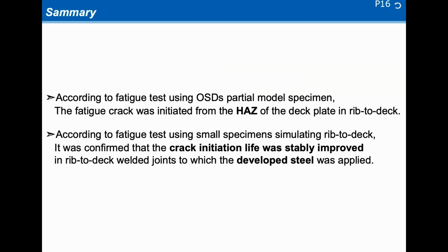Summary. According to fatigue tests using the OSD's partial model specimen, the fatigue crack was initiated from the HAZ of the deck plate in rib-to-deck. According to fatigue tests using small specimens simulating rib-to-deck, it was confirmed that the crack initiation life was stably improved in rib-to-deck joints to which the developed steel was applied.